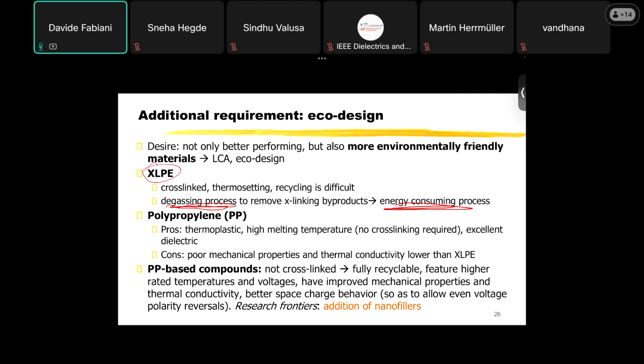So the idea is to use not a thermosetting material, but a thermoplastic material. The polyethylene is not good because the melting temperature is about 110, 120 degrees, so not very good to work at high temperature, but the polypropylene is a very good candidate because the melting temperature is about 160 degrees, and is a very, very good dielectric material.